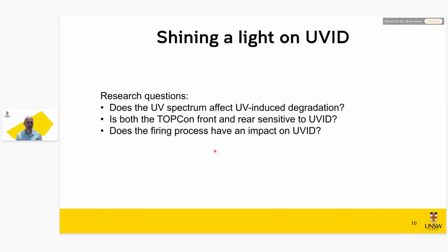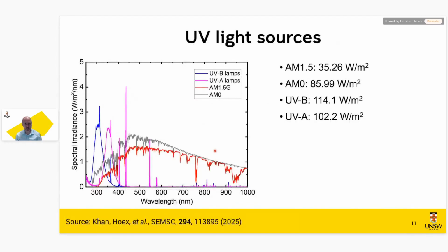And this actually gives us part of the puzzle to solve the mechanism, as I will show you later in the presentation. So what we did, and this was work that was published in August, we did stress testing with two different light sources. We had UVA, so that's harsh UV, but then we go harsher with UVB. So there's two different peak wavelengths, and the dose and the power was kept roughly identical. And you can see, if you compare it to the AM1.5 spectrum here in the red, that the AM1.5 has both UVA and UVB.